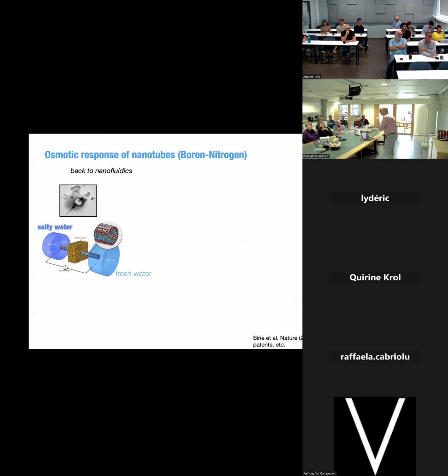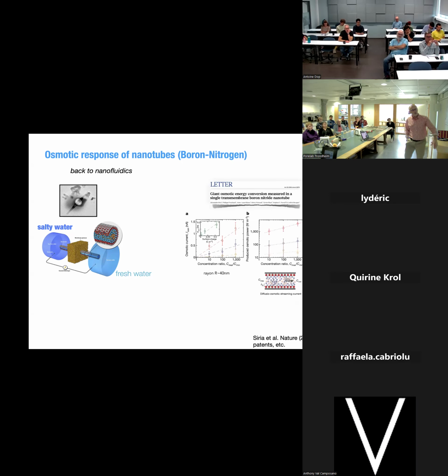The point is that I told you before that one key aspect was what happens to the membrane for osmotic energy with these two techniques, if you remember: PRO, pressure retarded osmosis, and reverse electrodialysis. The first experiments that we did on osmotic energy were the first nanofluidic experiments, not with carbon nanotubes but with boron nitride nanotubes. Boron nitride has the same crystallographic structure as carbon, except it's insulating. We put a difference of salinity between the two ends, but with a single nanotube. We didn't care about the membrane. Then we could measure the osmotic current versus the concentration ratio.